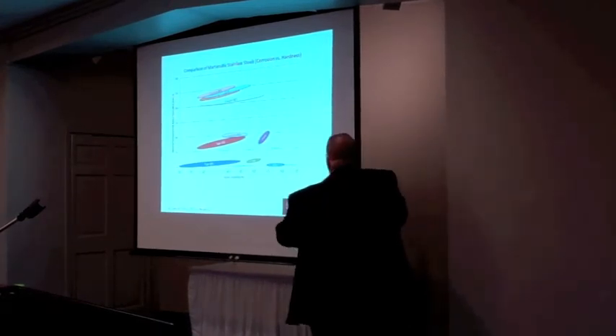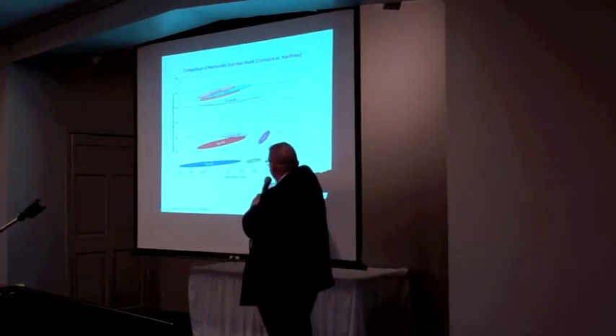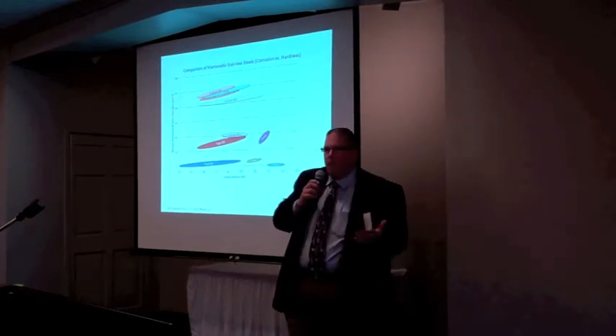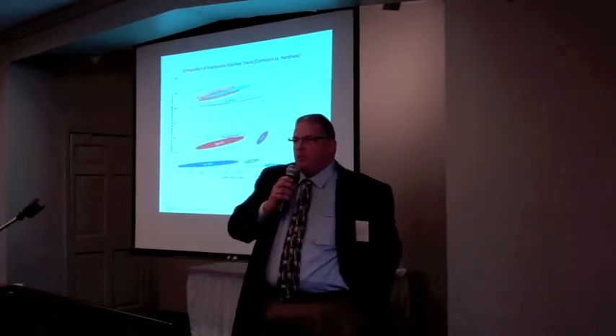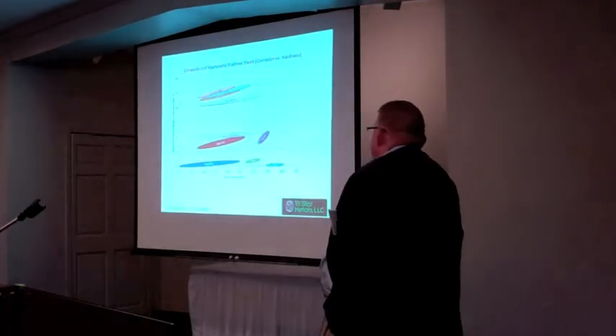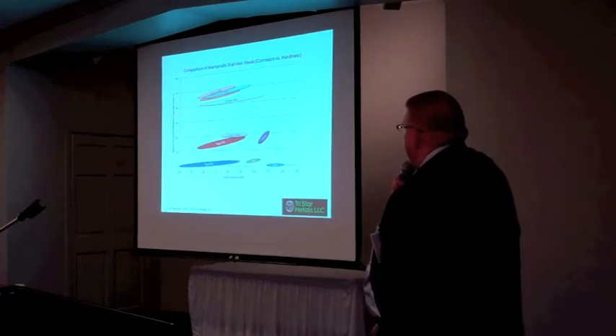Salt spray, quite frankly, for most martensitics, like the 440C, and I apologize if some of these numbers are hard to see, 420 and 410 are really a matter of hours typically. So it's really even too aggressive of a test to test those alloys. But they typically are going to fail in a matter of hours. When you start talking about a type 431 or a Trimrite material, you're closer to a 100-hour alloy.